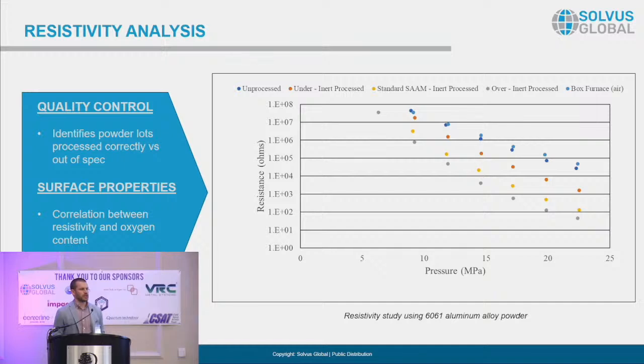Again, this is part of the quality assurance that we made sure that our tests, our procedures, match with what's needed in cold spray, right? Most of the powder bed processes, the laser DED processes, they're not too worried about small amounts of surface contaminants. They're not too worried about what the microstructure looks like because you're melting the material, right? You're giving that kind of normalization step, and we don't have that in cold spray.